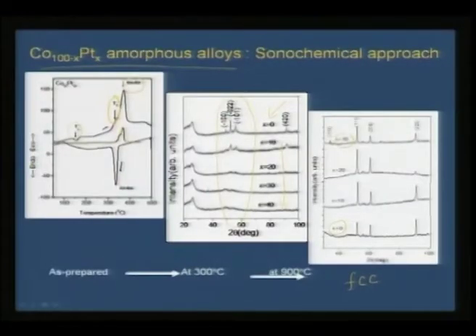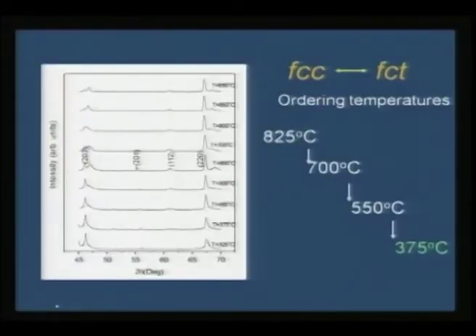So when you are heating it at 900 degrees C, you are able to stabilize an FCC pattern at room temperature, which means this is a metastable phase. So in nano form, when you try to prepare compounds, you are essentially able to successfully stabilize metastable phases for a cobalt platinum series.